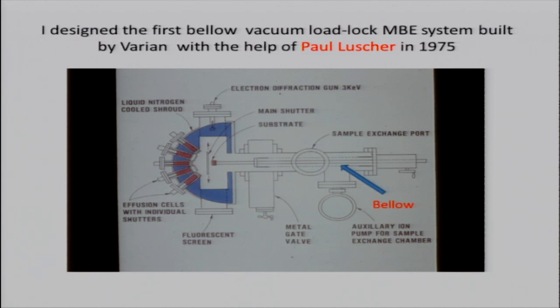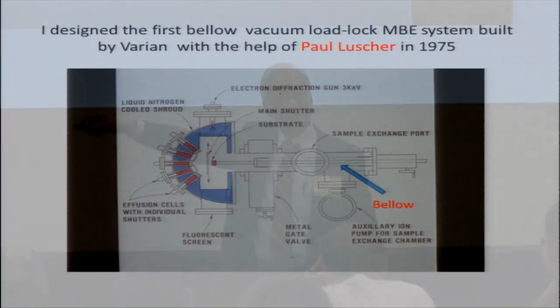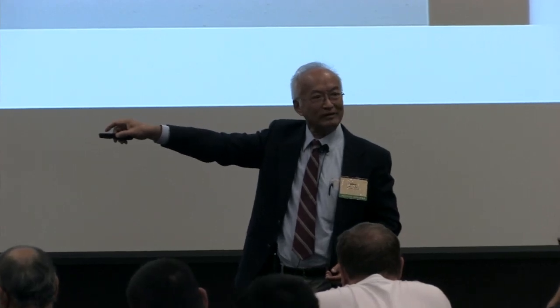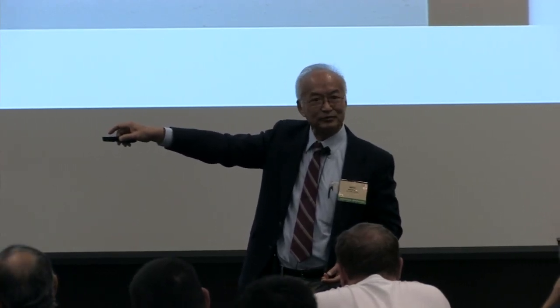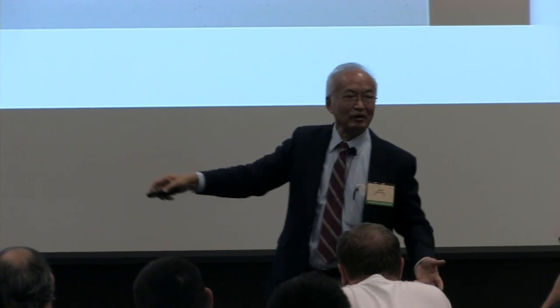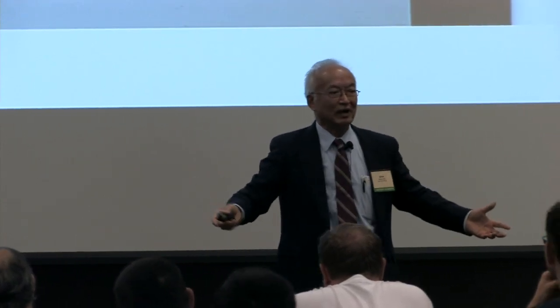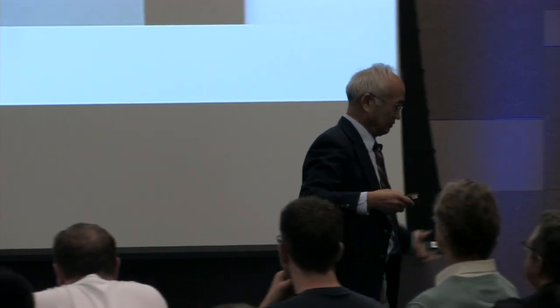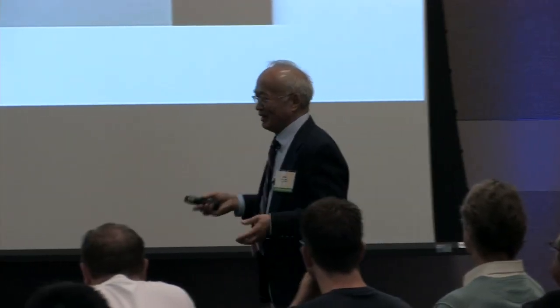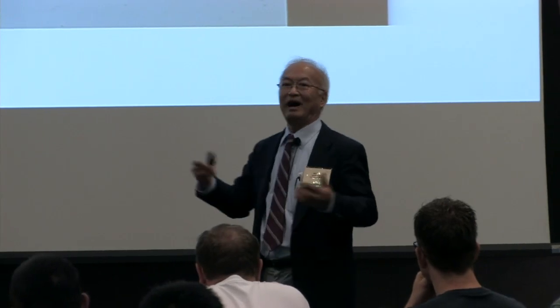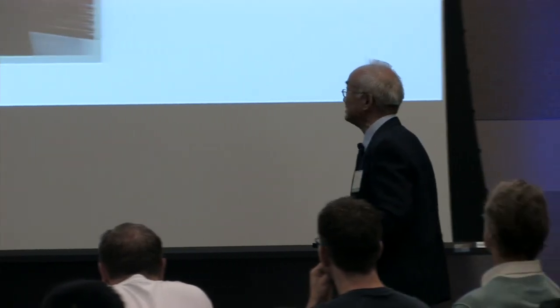The problem is, while you're growing, you cannot close the gate valve because the big bellow, this rod, is in the way. So we had to grow with that bellow exposed to the growth chamber. As you know, bellow had a lot of surface area, absorbed all the contaminated air and water. And even pump down 10 to minus 9, 7 was better than opened up to air every time you open, changing the sample. But it's improved, but not ideal. So we go on to the next generation.